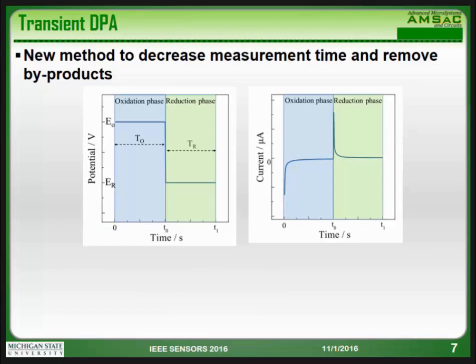So here comes our new method. We propose this new method to decrease the measurement time and to remove the byproducts. Here shows the stimulus of our electrode. We apply two potentials, the oxidation potential and the reduction potential, to react the targets and then reverse the byproducts. And here shows the signal output.